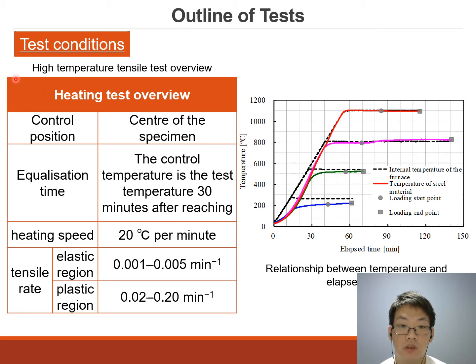The heating control position was set at the center of the specimens. In addition, the heating speed was 20 degrees per minute, and the soaking time was 30 minutes. Furthermore, the tensile speed was determined in accordance with JIS G 0567.